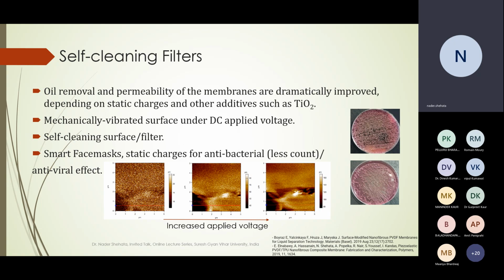Not far from these applications are self-cleaning filters. PVDF could be used in some cleaning for water, or between solutions, depending on the static charges on PVDF and the electric field that you can generate from mechanical excitations. So you can remove oil using these PVDF membranes, but in some cases it's highly preferred to add more catalytic structures within the PVDF nanofiber to enhance the efficiency of such filters, such as adding titanium oxide nanoparticles.